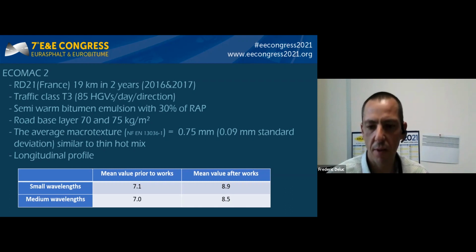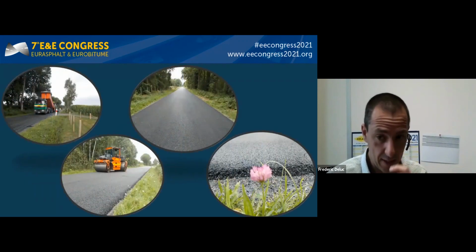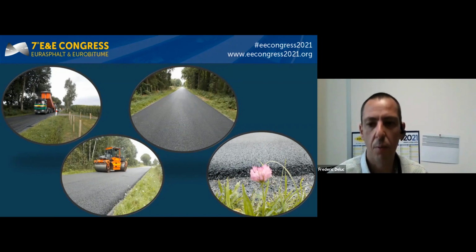This project resulted in greatly improved pavement ride quality. As you can see in the table, the longitudinal profile analyzer results have increased by almost 2 units. The next slide shows some photos of the laying process for this project, which used a paver and a drum roller. Aesthetically, the pavement is very similar to a hot mix.